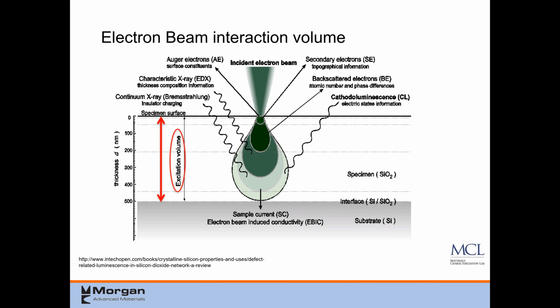And we consider the entire volume that's affected by the electrons interacting as the excitation volume or the activation volume. So when someone asks, well, can I look at something that's a couple of nanometers thick? The answer is no, because the information actually comes from deeper than that. So you're really passing through something that thin. This is more of a micron technique rather than a nano technique.